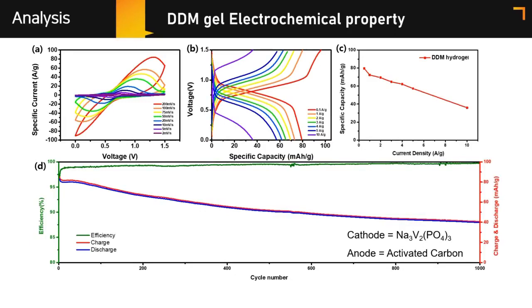This page is DDM hydrogel full cell data. Cathode is NVP and anode is activated carbon. Electrolyte is DDM hydrogel electrolyte soaked in water-in-salt solution, 15 molar concentration NaClO4. Graph A is the hybrid battery full cell graph. B is the GCD profile obtained at different current densities, and C is a plot of specific capacity versus current density.